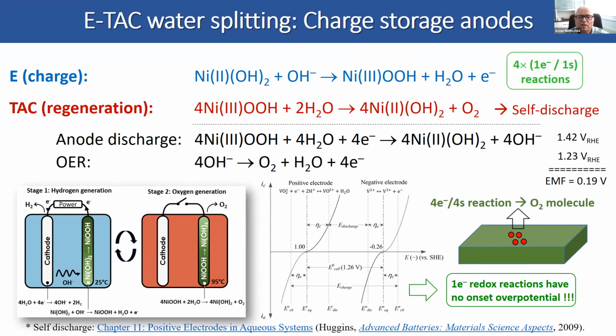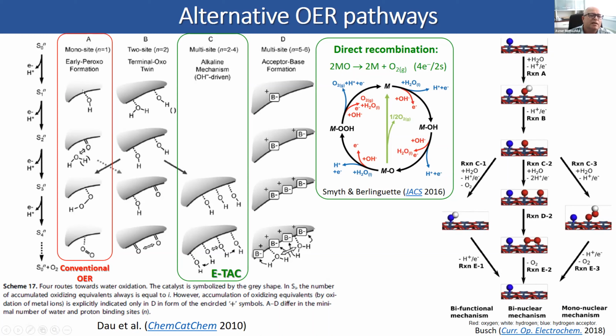And that is shown here. So, there are different pathways for oxygen evolution reaction. That's a slide from a review article that was published about 10 years ago. The conventional electrocatalytic material goes by this 4 electron per 1 site reaction that is shown schematically here, where we go with a different mechanism where we suppose, okay, we haven't proved this yet, but based on literature on this material of past research, we think that the mechanism involves 4 sites, which help you to divide the reaction over 4 sites, help you to reduce the overpotential. And there are different alternative pathways. Currently, we are looking into the different possibilities and trying to figure out what exactly is the reaction pathway in our system.